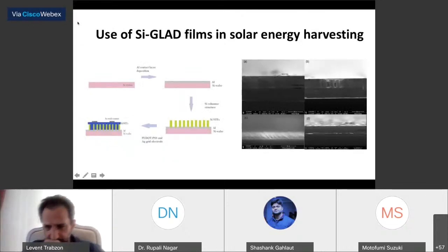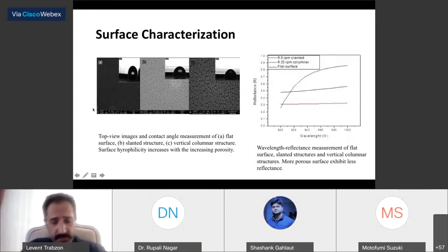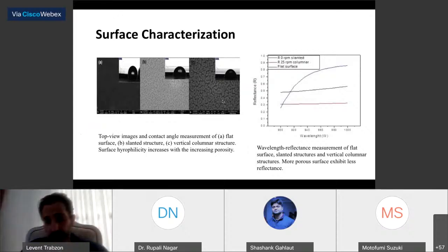A couple of years ago, one of my Master of Science students tried to develop silicon GLAD films for solar energy harvesting, solar cells. Actually, what we are trying to do is make porous silicon films embedded in the polymer PEDOT:PSS, so that we can harvest electrons from the solar energy. Anyway, these are some of the pictures we have got, and we also characterized material properties, like surface hydrophilicity increasing with increasing porosity, as you see on the surface. That is also related to the previous results.